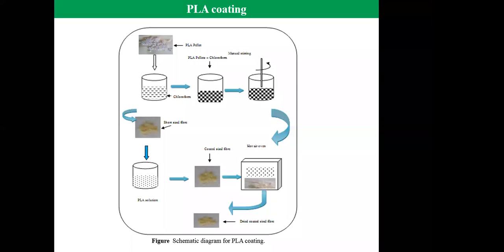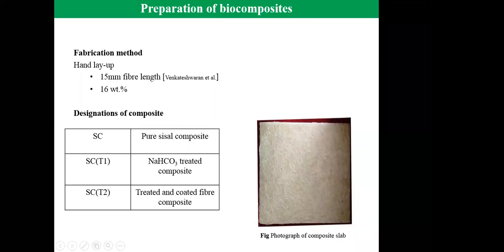These treated fibers were again coated using PLA, polylactic acid. PLA pellets are there, you can see, and chloroform. These pellets are immersed into chloroform. Then manual stirring is done. In this solution, the treated fibers were immersed. Thereafter, after coating, these fibers were kept in a hot air oven and dried. The coated treated fibers are shown here.